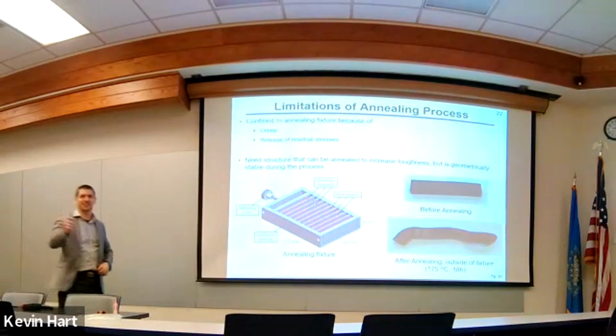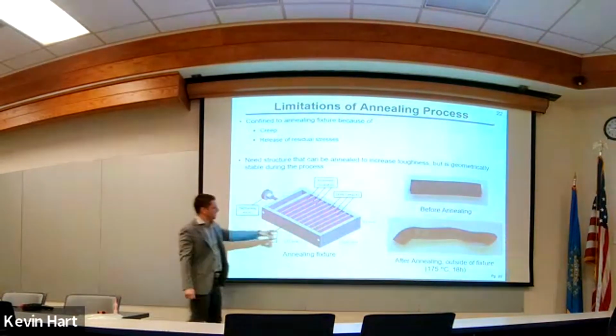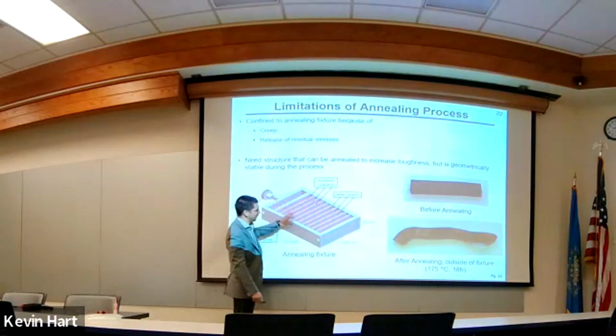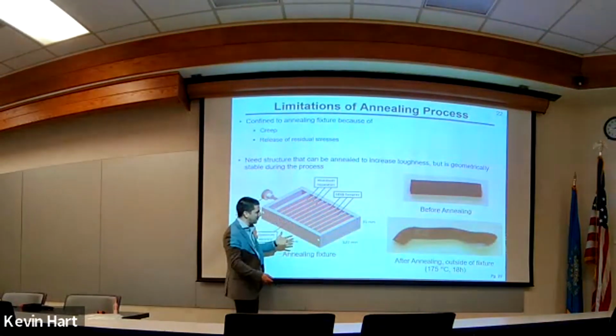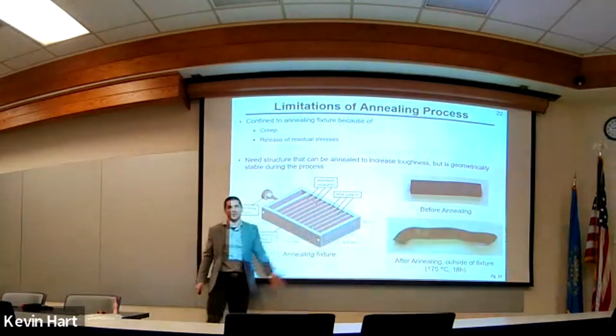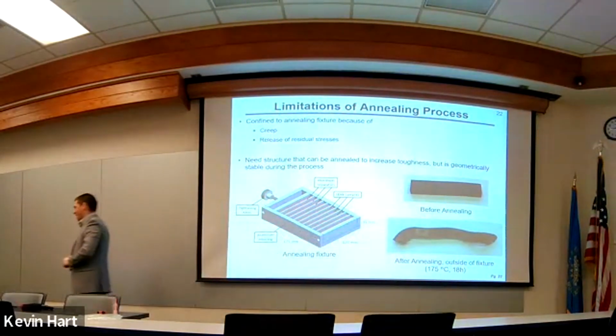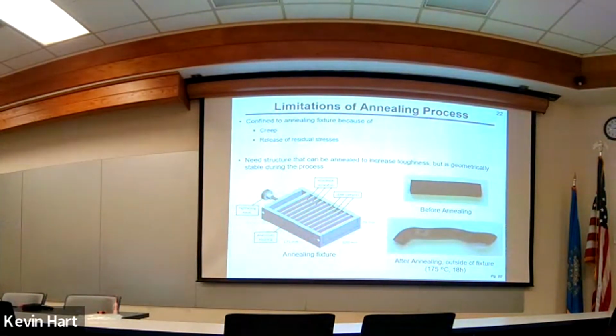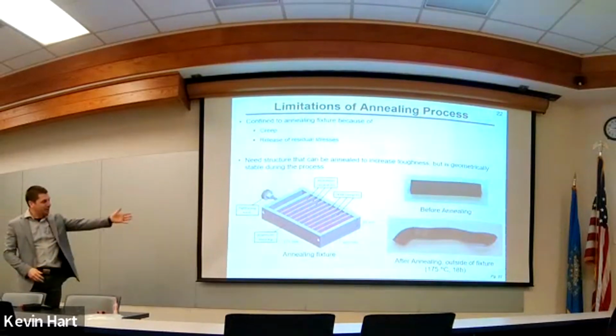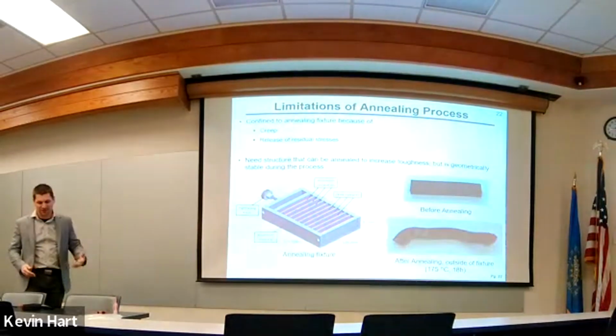All right, shame, shame. We put these single edge notch bend specimens in this aluminum mold, and if you're going to 3D print something, why use a mold in the first place? So if you were to actually take that single edge notch bend specimen and try to anneal it outside of a mold, it looks like this. Okay, so we'll pass this one around too. Don't break that one; it's very important. I'm just kidding. You can break it if you want. So if you try to do this annealing outside of the fixture, it looks like that.